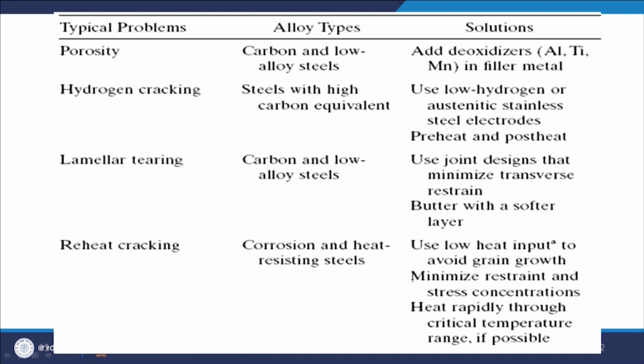Now, we will see some aspects of the weldability of transformation hardening metals, a typical one being steel. The factors that govern the weldability of steel include the following. Whenever steels are welded, they show a tendency for porosity formation, mostly low carbon steels. Some medium carbon and high carbon steels and alloy steels show hydrogen embrittlement as well as lamellar tearing tendency, and some chromium molybdenum steels used for high temperature applications, as well as some alloy steels, show a tendency for reheat cracking.